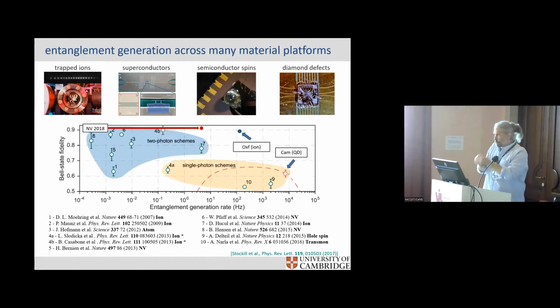But the spin coherence, if you don't do anything, is around 1 to 2 nanoseconds. The photon is about a nanosecond, roughly, or a bit less. So you're starting with a big hit already. You need to improve the T2 star so that it's 1% limit or 0.5% limit or 0.1% limit. So the T2 star needs to be long. And we figured out in the community a way to do this so that we can reach 10 nanoseconds or 100 nanoseconds now. So that becomes possible. That would be the second number you have to care about: the time it takes to generate a photon versus your T2 star.